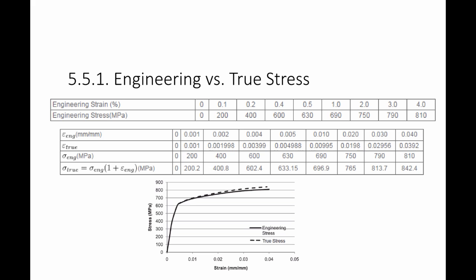I've calculated the engineering strain values — multiplied by 100 to express as percent. The true strain is calculated using the equation relating true strain to engineering strain, and you can see they are very close until higher strains, at which point they start to deviate.